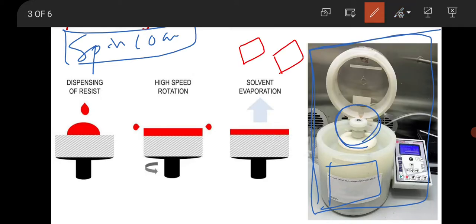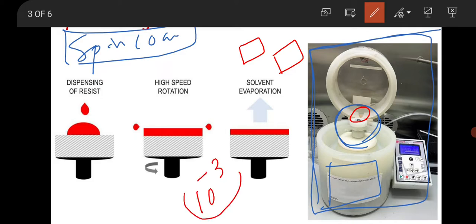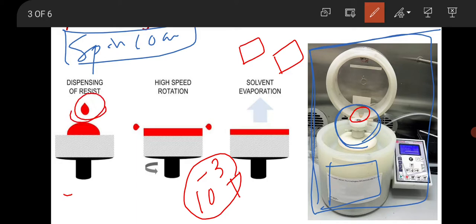You have to place your substrate, which is basically a glass, FTO, or ITO — a piece of glass — onto this nozzle. You have to start your rotary pump, which will provide a pressure of about 10 to the power minus 3 Torr. By this pressure you can hold your glass substrate in the downward direction so the substrate is fixed in this position. This is the first step — you start your pump and suck the substrate from below to hold it stable. Then you insert your liquid, which is the chemical precursor, onto this glass in a dropwise manner.